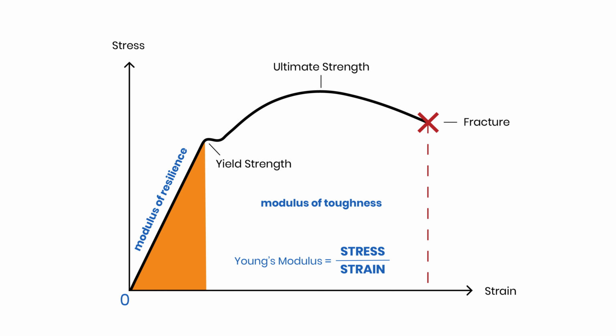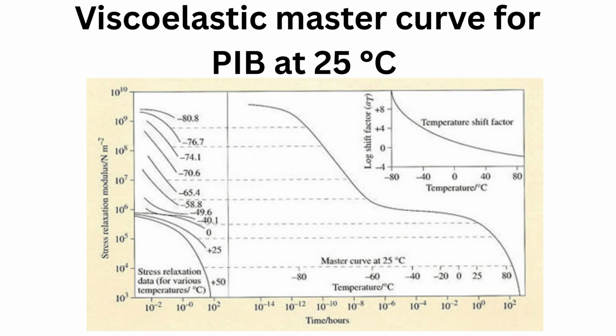of time. Time-temperature superposition. For amorphous polymers above their Tg, there is a convenient approximation which makes experiments easier. It is known as time-temperature superposition, and it relates time to temperature for viscoelastic materials. A sequence of measurements of ER is performed at different temperatures at a fixed initial strain. The timescale might be limited between several seconds and, say, 100 hours.